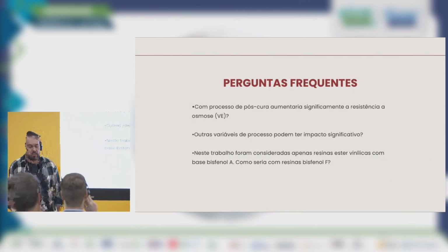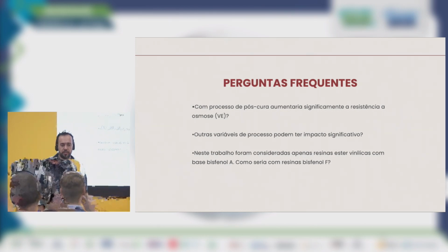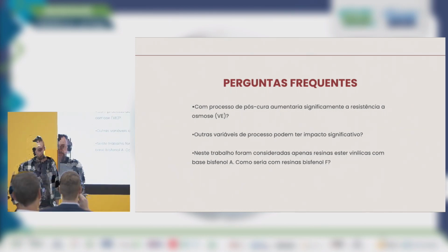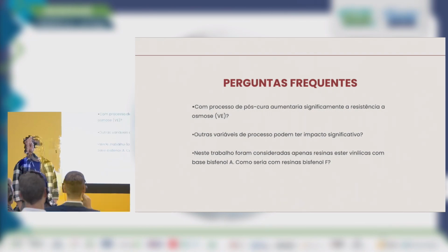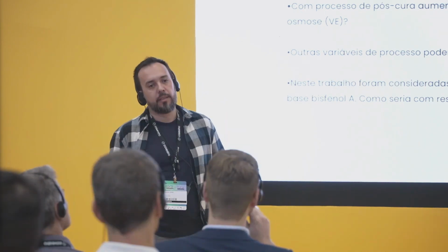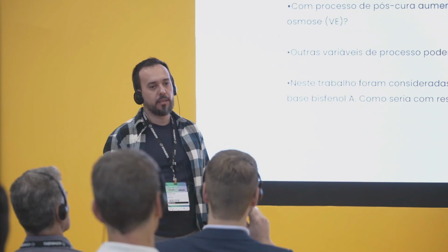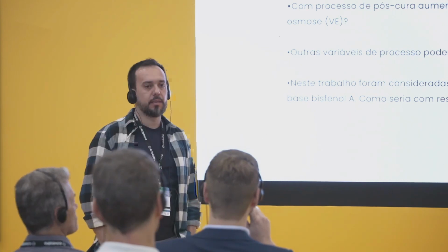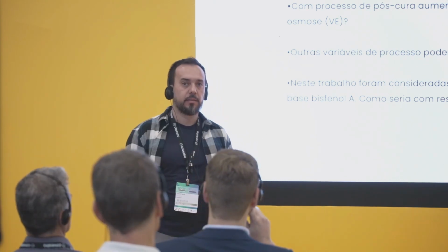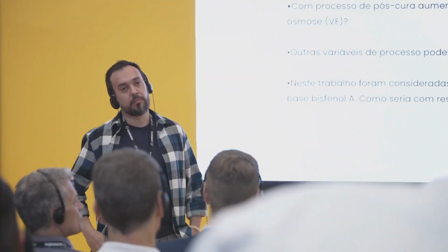I have a query with regard to some of the questions. The post-cure process. Would you agree that the test that you applied, 100 hours at 66, doesn't that guarantee a greater than 90% post-cure, because usually it's 80 degrees for 8 hours or 60 degrees for 24 hours. The test in itself perhaps may have guaranteed the cure somehow.